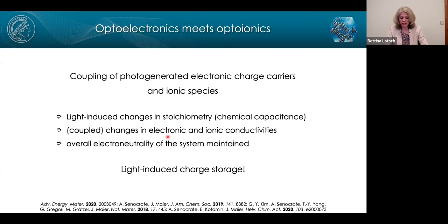We see changes in the electronic conductivity of the carbon nitride upon photoirradiation. We're not quite sure whether we also see changes in ionic conductivity. That is quite difficult to verify. And all of this happens while keeping overall electron neutrality of the system. To summarize, what we see here is basically light-induced charge storage. And that is something that we currently study for various types of applications or properties. The first and easiest is to try and use this temporary charge trapping to decouple the light excitation from the actual photocatalysis. So basically to do something like dark photocatalysis. And what I mean by that is shown here.